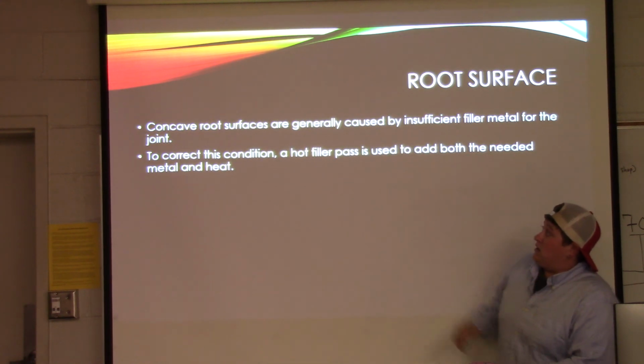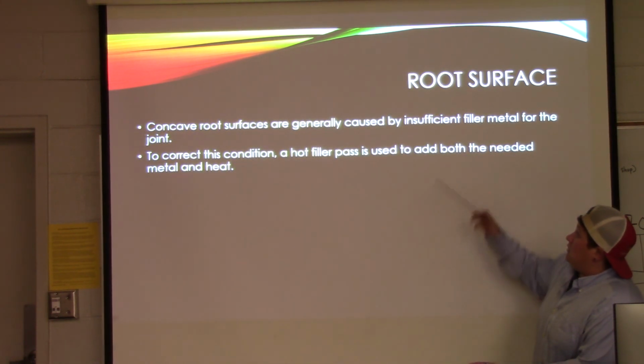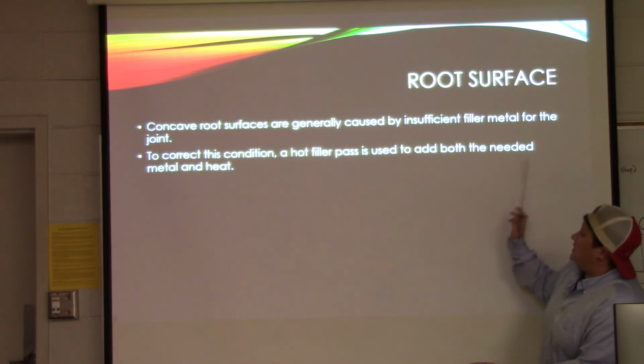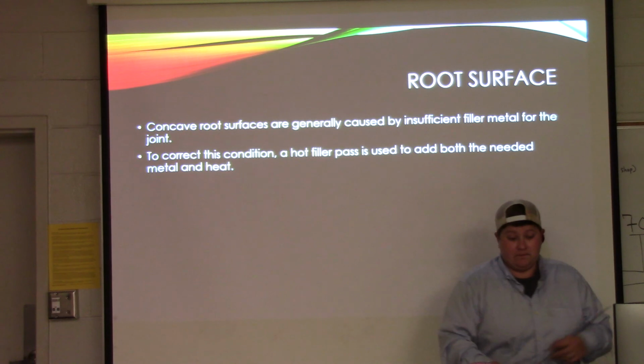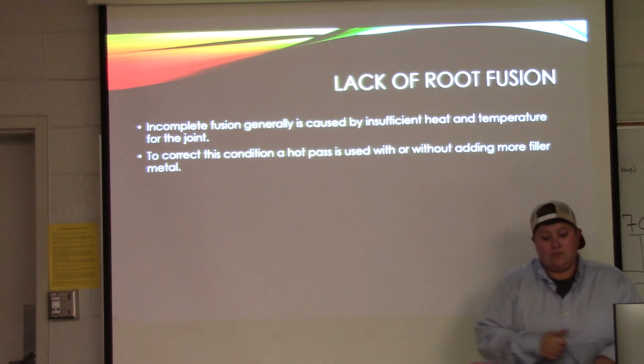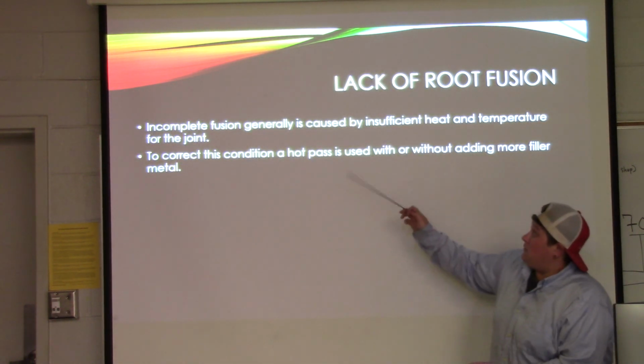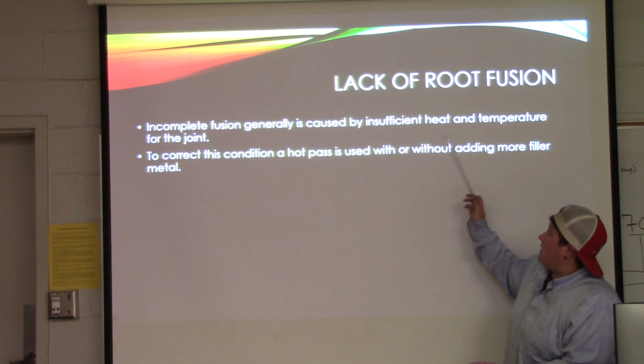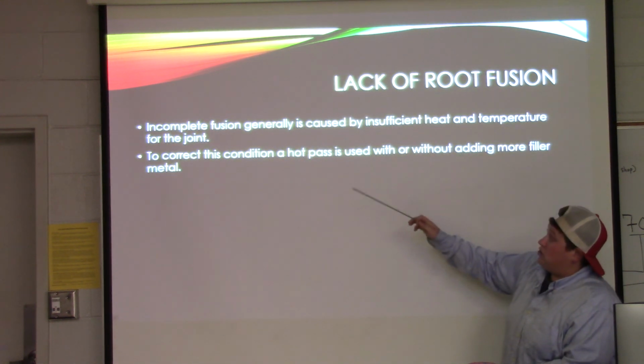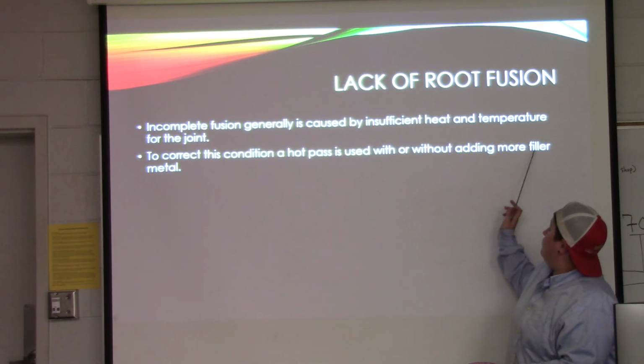Root surface. Concave root surfaces are generally caused by insufficient filler metal for the joint. To correct this condition, a hot filler pass is used to add both the needed metal and heat. Lack of root fusion. Incomplete fusion generally is caused by insufficient heat and temperature for the joint. To correct this condition, a hot pass is used with or without adding more filler metal.